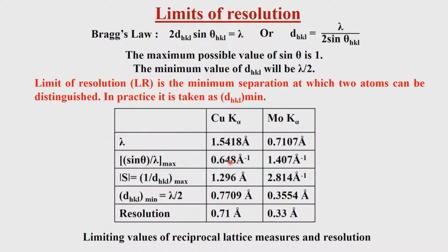So, obviously, if you are looking at measurements for covalent interactions and intermolecular interaction understanding in molecular crystals, copper is a no-no. You have to use molybdenum and other lower diffraction wavelengths, so that we can essentially get to the accuracies which we are looking for.